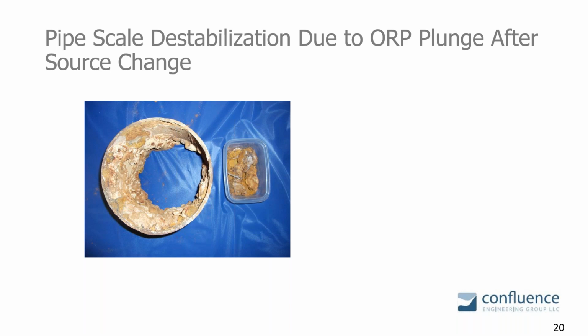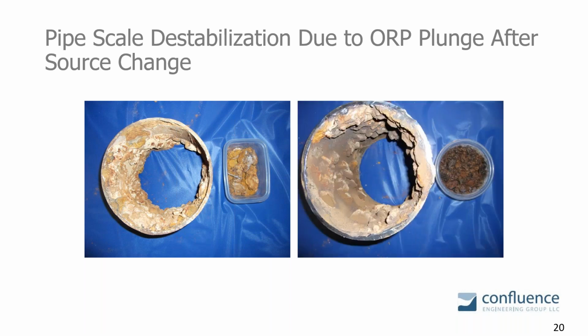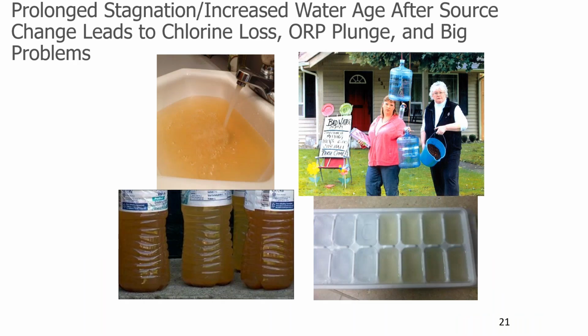After they introduced a new source of supply from the alternate side of the distribution system, this area became stagnant. The water mounded up in this area, became stagnant, and they lost their chlorine residual, and it literally dissolved the iron scale off the pipe. And this is now what the tubercles and the materials that were flushed out looked like coming out of the distribution system. And this occurred over miles and miles of pipe. This is what happened at the tap. This discolored water coming out of the tap, the ice trays.